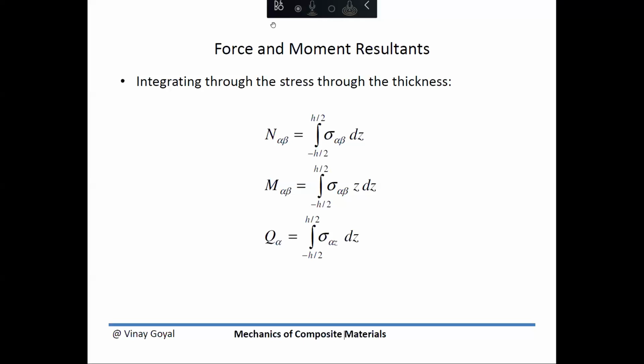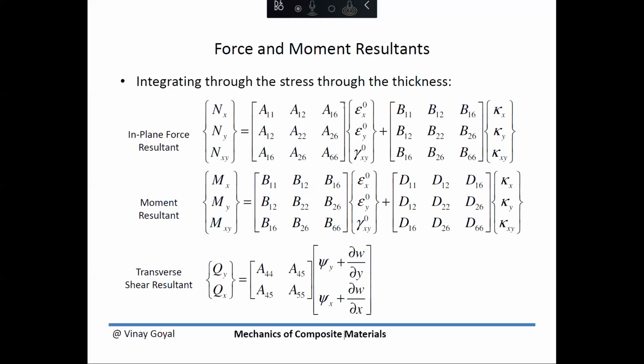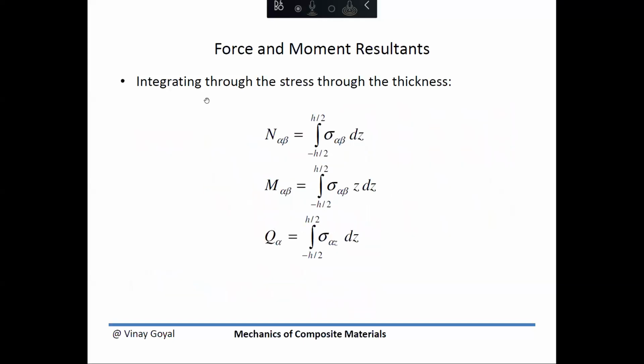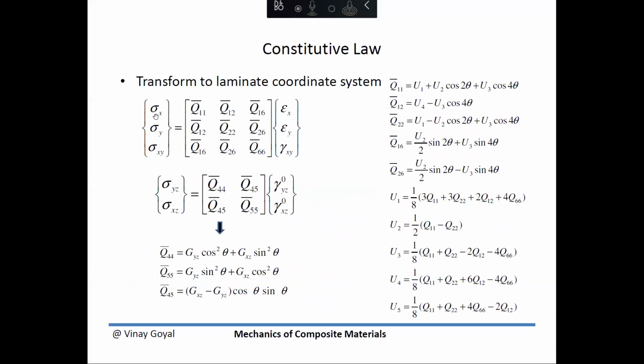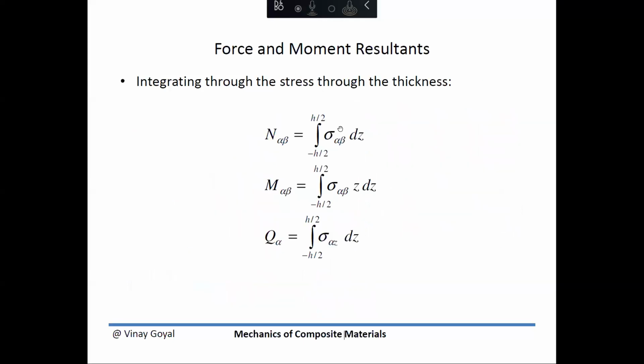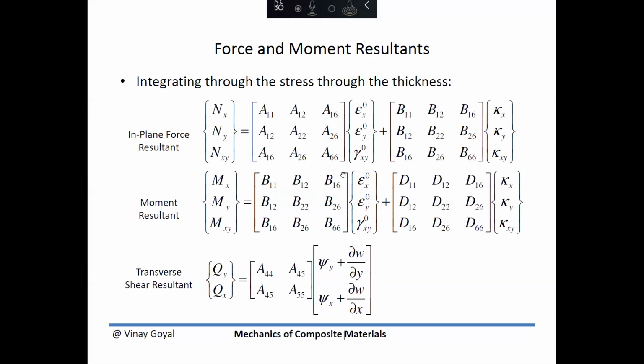And so continuing here, what we got now is that we can now write through a thickness, integrate these equations. And these equations are these ones here. These stresses were given like that. So we can integrate it through a thickness from the bottom ply to the top ply. And what we found in the classical plate theory is that the in-plane force resultants and the moment resultants can be related to the curvatures and the mid-surface strains, in-plane mid-surface strains, and the curvatures, through the ABD matrix. And that has not changed today.